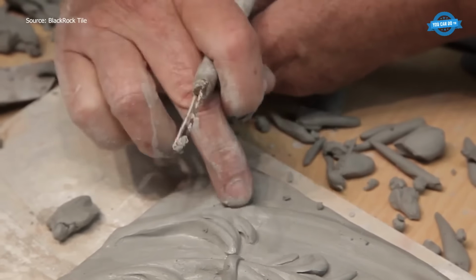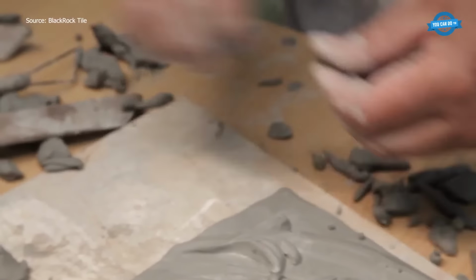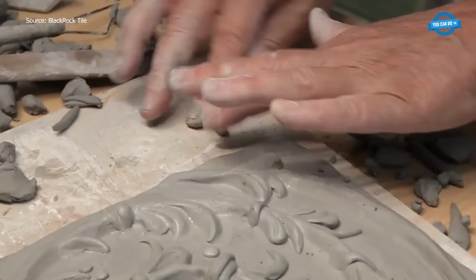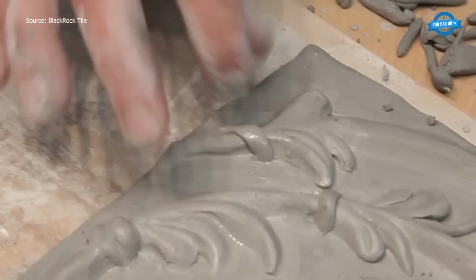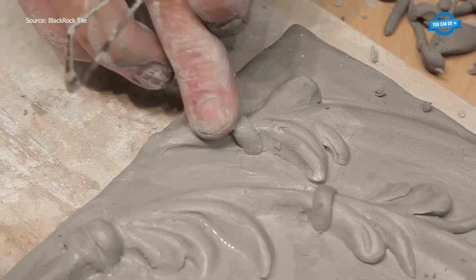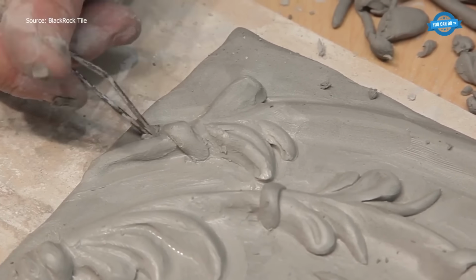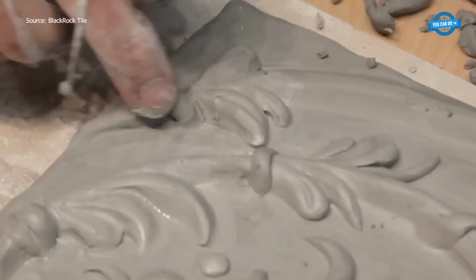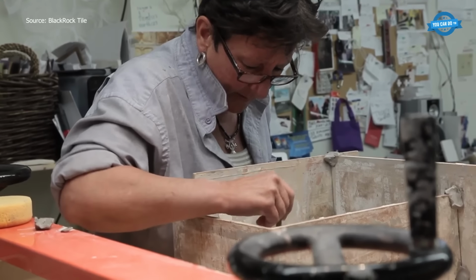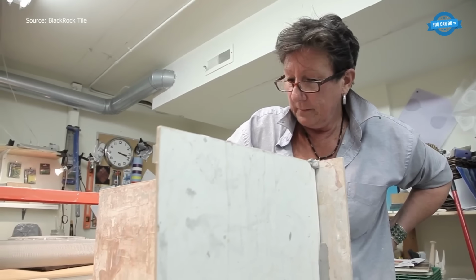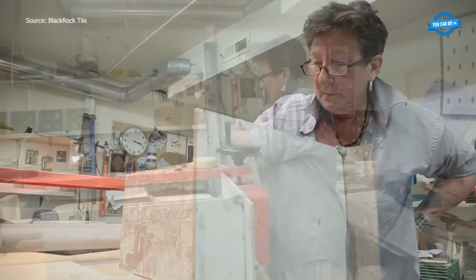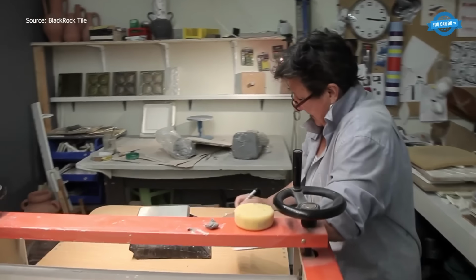After drying, edges are refined and surfaces adjusted to maintain dimensional balance. Bisque firing strengthens the structure and sets the base for glazing. Technicians apply custom glazes by hand, layering tones to create depth across every piece. No two tiles leave the table exactly alike, and that individuality becomes the whole point. A second kiln cycle fuses glaze in clay into a durable finish suited for kitchens, baths, and commercial interiors.